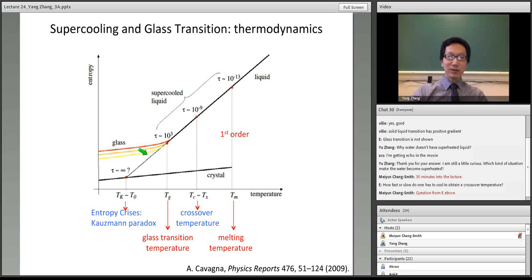The other reason why crossover phenomena is more important is that in this temperature range, the system is metastable. So it's still near equilibrium. So ideally, it doesn't matter how you cool down the system. You can always get the same crossover temperature. But for the glass transition, that is different. The glass transition is really a transition from an ergodic state to a non-ergodic glassy state. So that depends on the cooling rate or the thermal history. The crossover temperature is more like a thermodynamic crossover phenomenon. So it doesn't really depend on the cooling or heating rate.